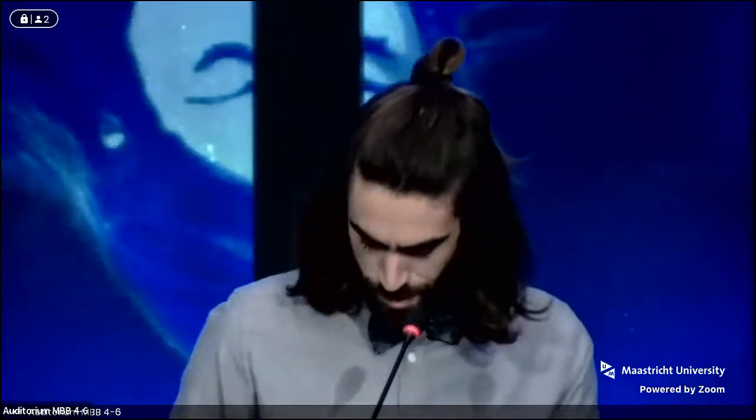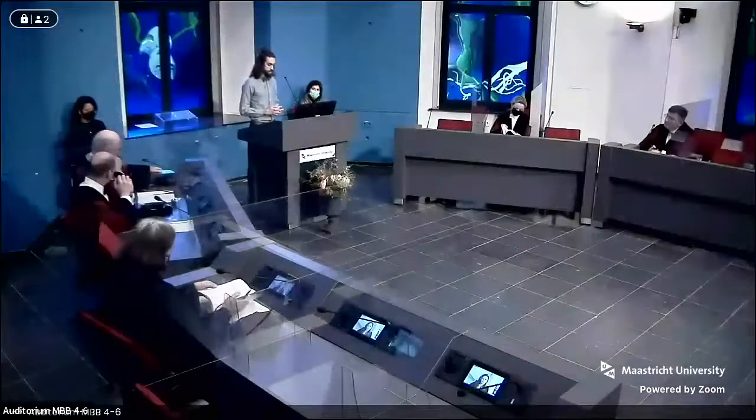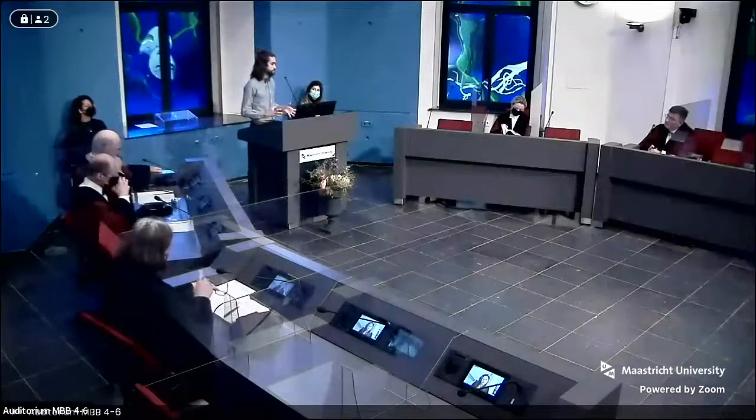You form collagen 1 fibers in their native state, showing the banding that is maybe even visible in this image, by giving it the right conditions: pH 7.4, some ionic content in solution, and the presence of a phosphate buffer helps. And that was it. After some optimization, we were able to obtain them.